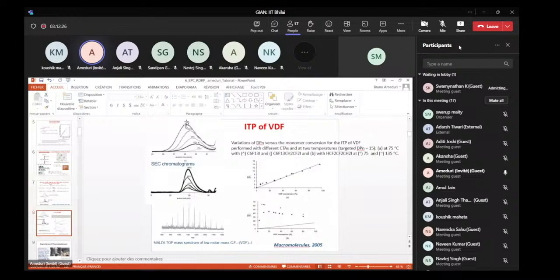You can see up to 70%. Okay, this is 50%, 30%. So we have a much higher molecular weight and a kind of narrowing of the dispersity, with a control. I told you this is the evidence of a controlled polymerization, while on the third case, sorry, you have an increase and then a decrease showing that this chain transfer agent acts as a chain transfer agent in telomerization rather than in controlled radical polymerization. Interestingly, the MALDI was very nice and very narrow also. We have a nice dispersity by MALDI, showing that in the 2 first cases we had this tendency of controlled polymerization.